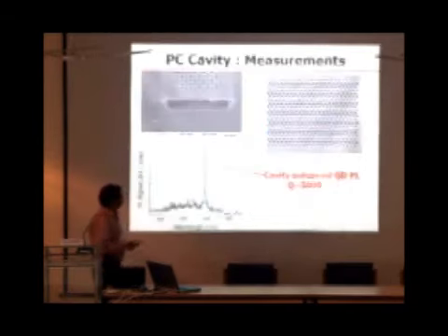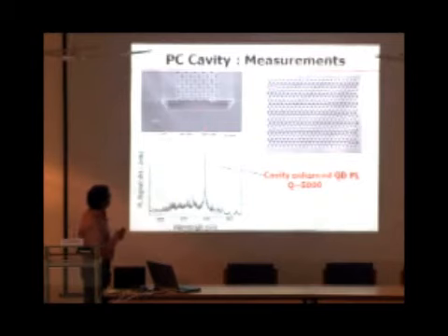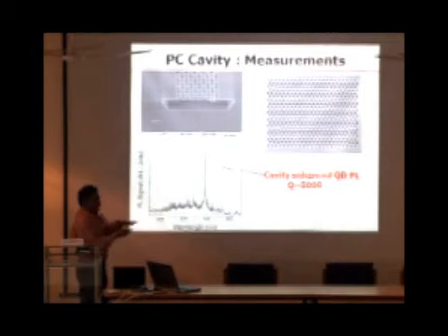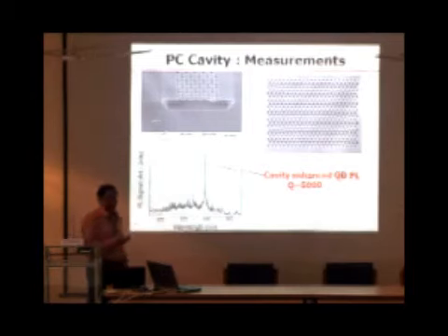So this is one of our results - the so-called air bridge structure or membrane structure, where we make the air hole pattern on a quantum dot structure, then remove the bottom aluminum gallium arsenide layer to make the membrane stand. The thickness of the membrane is typically 100 to 150 nanometers, achieved so that you have n equal to 1, air above and below, for maximum confinement. In addition, we modulate the thickness of this air layer so that the bottom is reflected and the top is emitted.